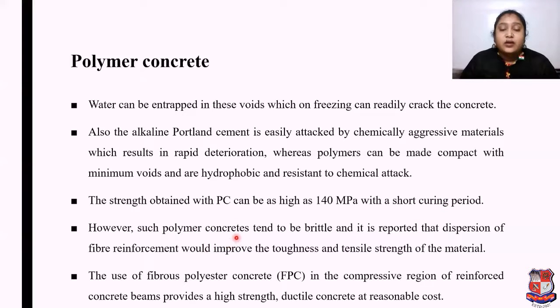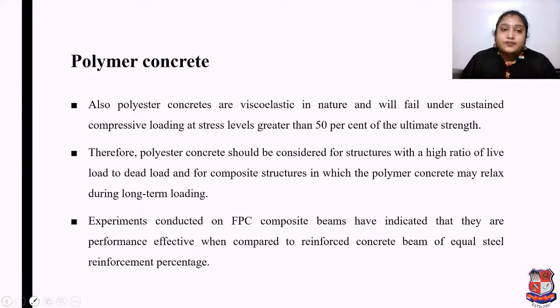However, such polymer concrete tends to be brittle, and it is reported that dispersion of fiber reinforcement would improve the toughness and tensile strength of the material. The use of fibrous polyester concrete, FPC, in the compressive region of a reinforced concrete beam provides a high strength ductile concrete at reasonable cost. Also, polyester concrete is viscoelastic in nature and will fail under sustained compressive loading at a stress level greater than 50% of the ultimate strength.